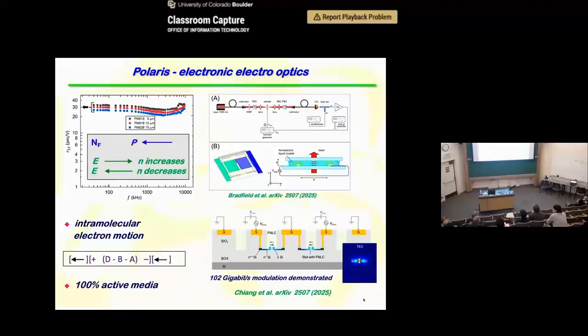So you take the ferroelectric nematic, so we've done precision measurements of the amount of delta n you get for a given field. So that's a coefficient R33. Measuring this as a function of frequency in the sort of megahertz kind of range. Turns out that the materials that Polaris can make, these are chromophores doped into the ferroelectric nematic, have a R33 that's comparable to lithium niobate, which is the standard sort of solid state ferroelectric used to do phase modulation.